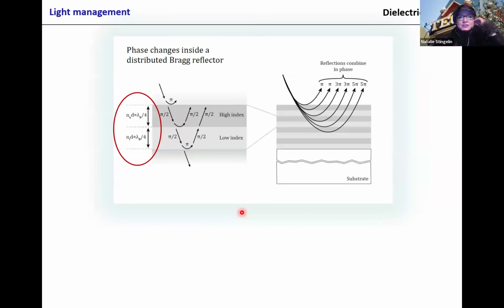So this is the structure I already showed you before, where we have multiple bilayers of a low and high refractive index. What is different to the anti-reflection coating I showed before is that here both of the layers—the gray, the high refractive index, and the light gray, the low refractive index material—they are of the same optical thickness. Optical thickness means the physical thickness, D, times the refractive index of that material.